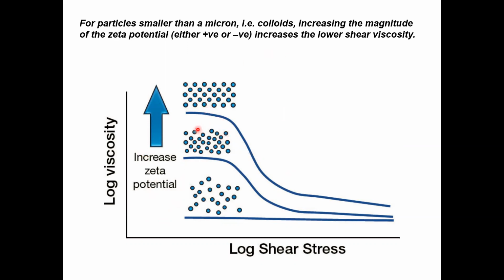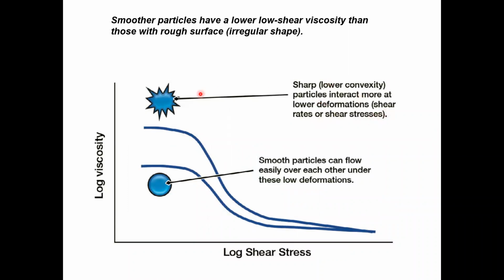Surface charge that you can get in colloidal solution, where you have your solid particles suspended in a colloidal medium, you can measure by the so-called zeta potential. So we look at the viscosity, and this is a log scale as a shear stress, strain rate, if you wish. Then you can see that at low shear rate, the surface charge on the surface of the particle will make a huge difference in viscosity. But when you go to high strain rate, this Coulombic interaction coming from the charged particle can be minimized, and the viscosity difference is not that great. Obviously, irregular shape type particle will give you a higher viscosity than a regular shape particle. That also at high strain rate doesn't make a big difference.